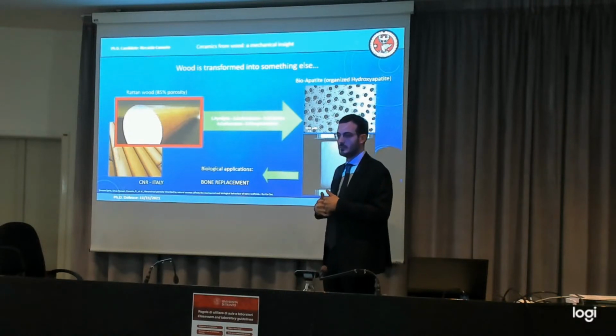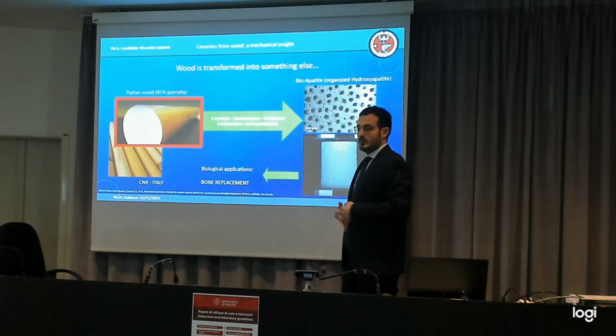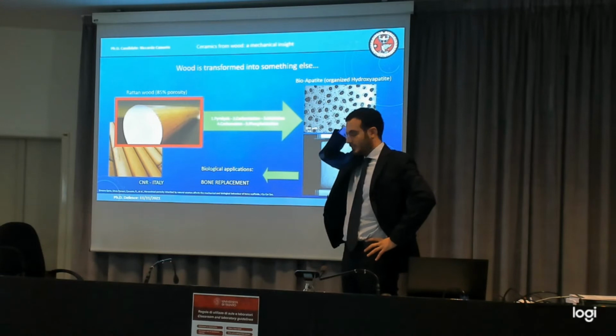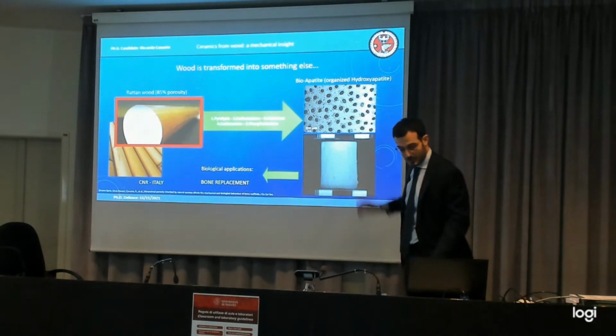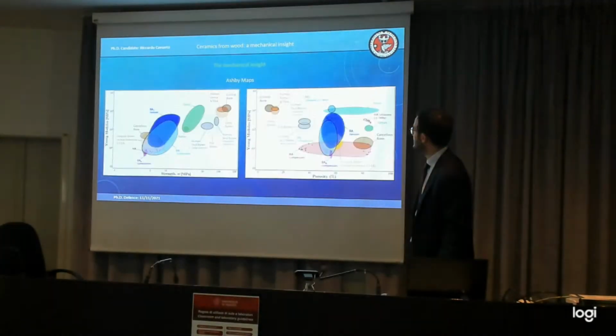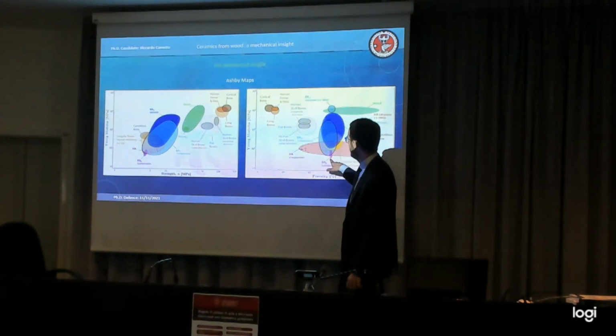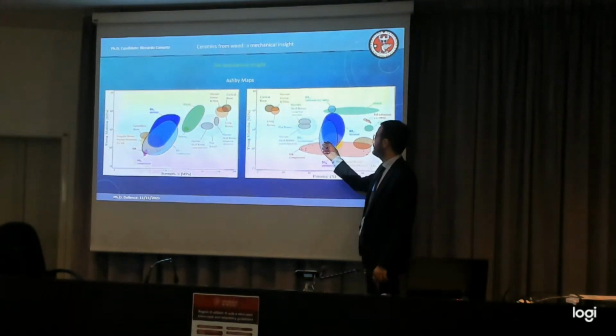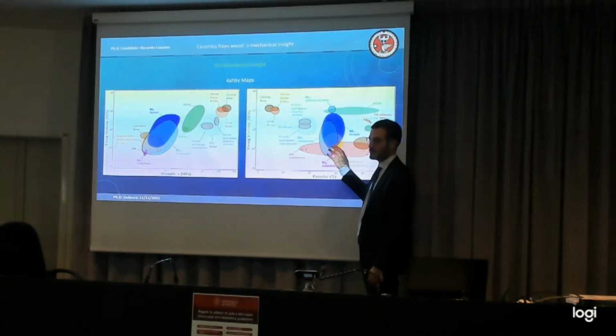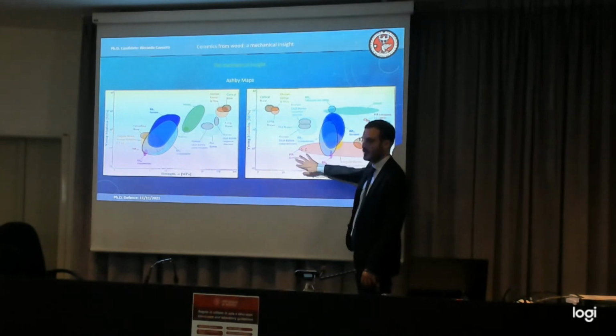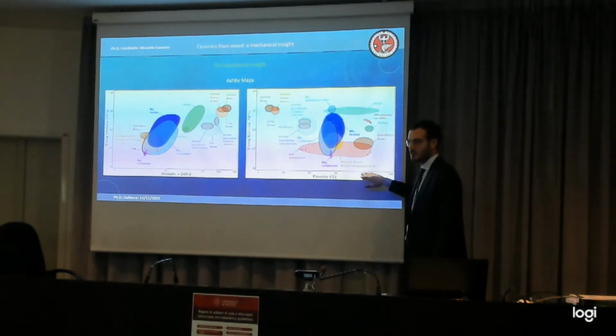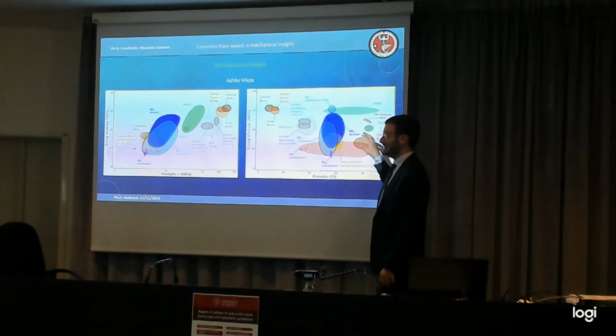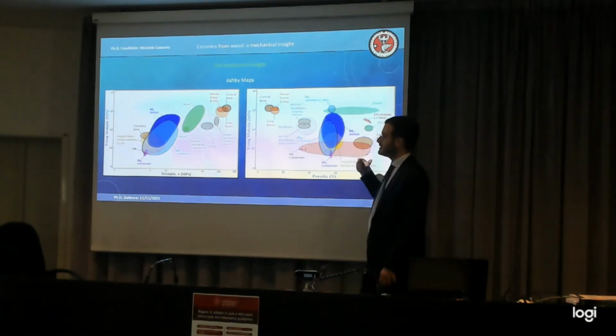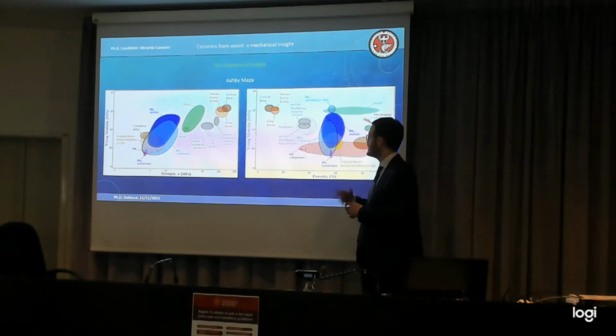So the increase in toughness that you observed is mainly due to the wood structure or to the porosity, like for sinter or incomplete sinter or porous ceramics? So it's responsible for the increase of toughness? Yes, the wood structure as well. It is mainly responsible because, as you can see from the Ashby maps, the average porosity between standard hydroxyapatite and this ceramic is almost the same. The range is almost the same. You see, there are some with a lower porosity, but some others will have higher porosity. So on average, it's almost the same. But with that level of porosity, you are obtaining something that is optimized. So you organize it in an optimal way, and that is immediate in the result.